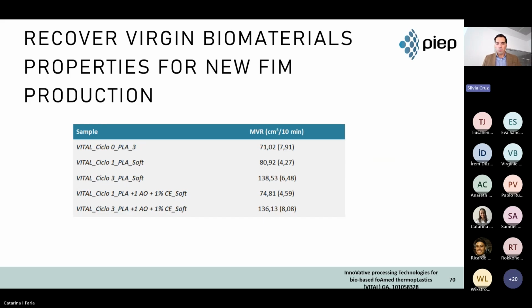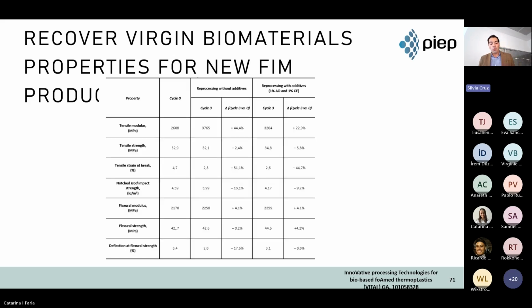What we also performed was, in the end, to double check the mechanical properties of these materials from this approach. And what we got is a slight improvement when we compare the non-additivated with the additivated materials. Just to remind you that we made 100% recycle of material. So we were not diluting the material with virgin polymer. We were speeding up the degradation. And since we were speeding up the degradation, we got degradation results in the end.